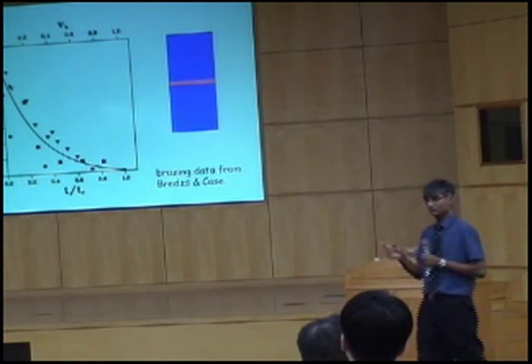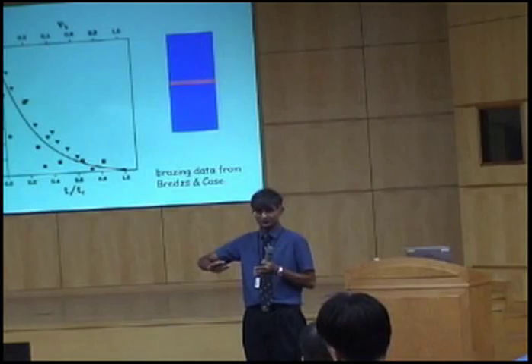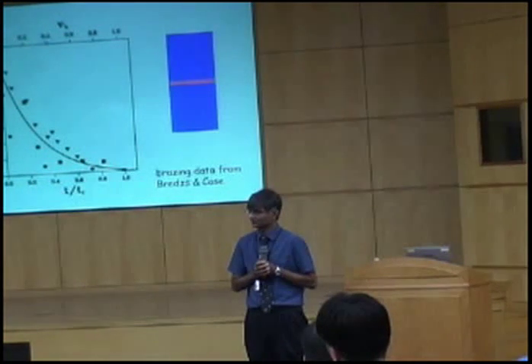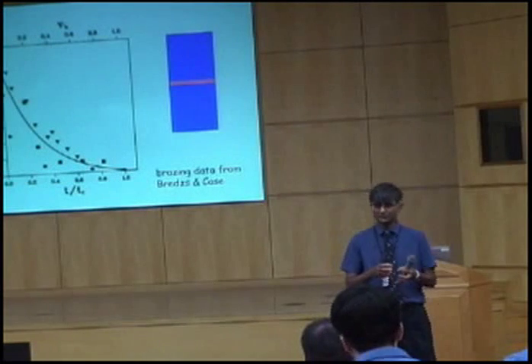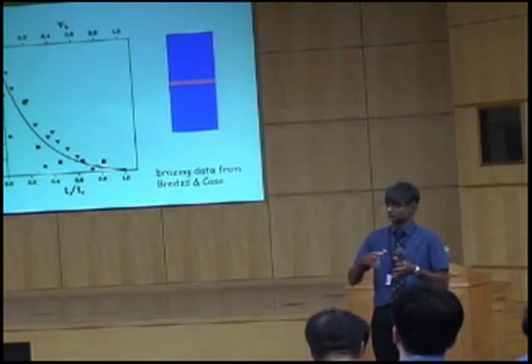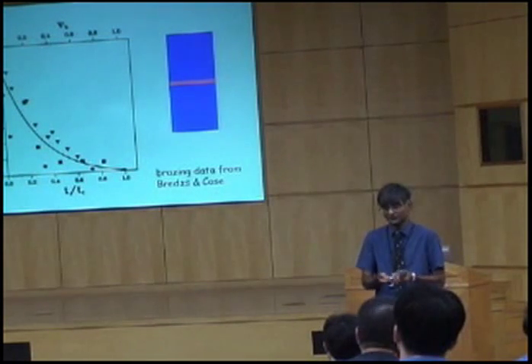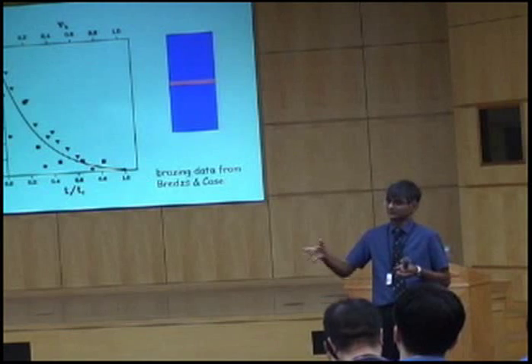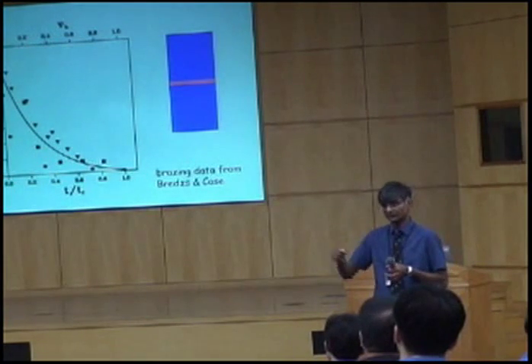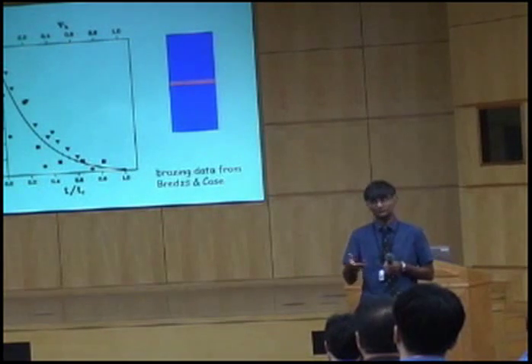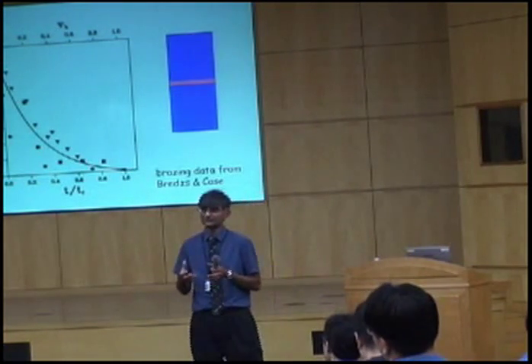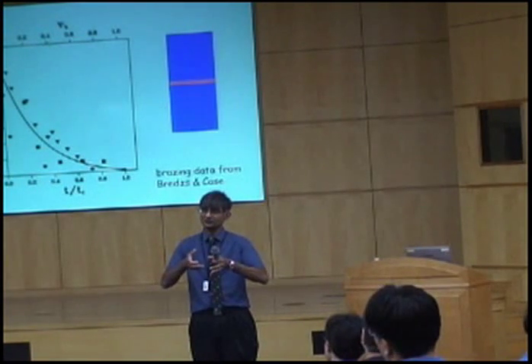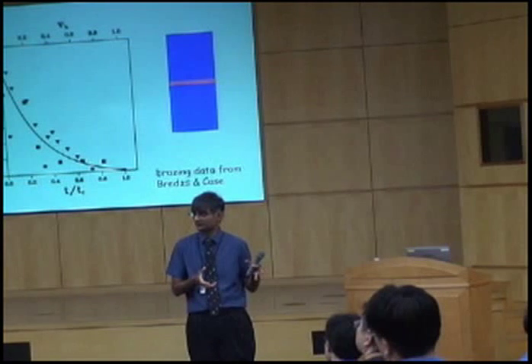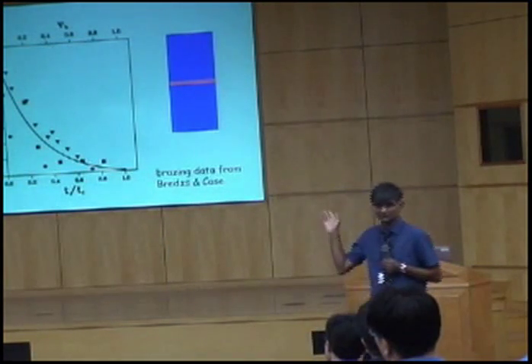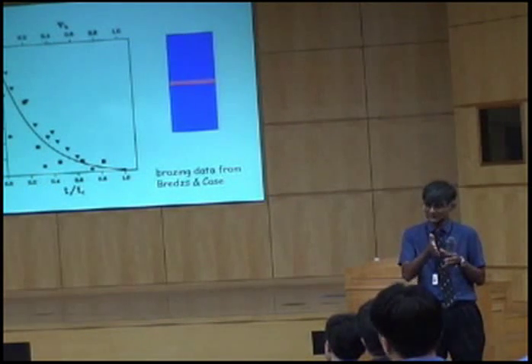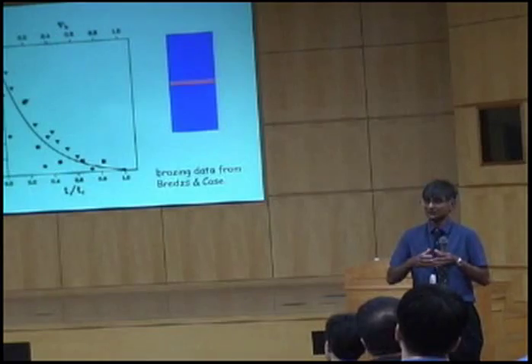So it's very interesting, if you actually make your layer of glue or brazing material thinner, then your joint becomes stronger. Okay? So when you have a strong material and a weak material and you put them together, the strong material will stop the softer material from deforming. So the yield strength of the softer material increases. At the same time, the yield strength of the harder material decreases. And this is exactly what happens also in dual phase steels, where you have a mixture of ferrite and martensite. The ferrite actually yields at a higher strength than would be the case if it was 100% ferrite. Okay. Now we can use this curve, which comes from brazing experiments. Braze is basically a soft material which you put between two bits of steel to make a joint.